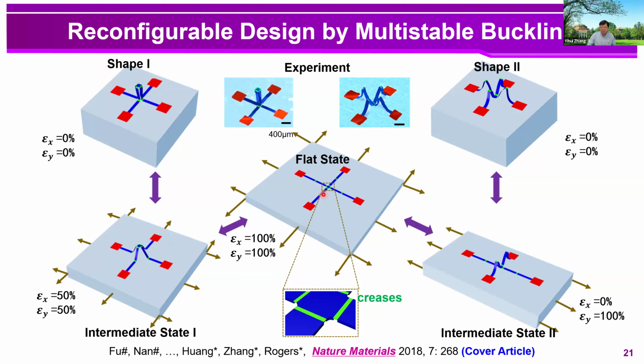But if you instead use the sequential release by releasing the x directional strain first and the y direction second, the x directional ribbon will form 2 waves first because of the constraint from the y directional ribbon. And after that, if you further release the remnant pre-strain along y direction, the entire structure will be trapped into this 2-wave mode, and finally you will get this shape 2 configuration. This means that if you stretch and release with different sequences, the structure will be reshaped between the shape 1 and shape 2 modes. And this idea has been validated by our experiments at microscale.